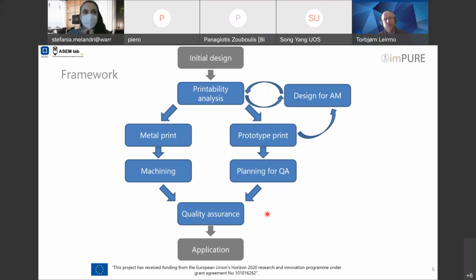For us, we have both tried with the selective laser sintering, which is for polymer powders, and also for fused filament deposition, which is the 3D printing technique, which is much faster. We were able to get quite accurate prototypes that enabled this planning for quality assurance. But of course, the selective laser sintering is much closer to the metal printing, which is a better fit for actually predicting and evaluating the final properties.